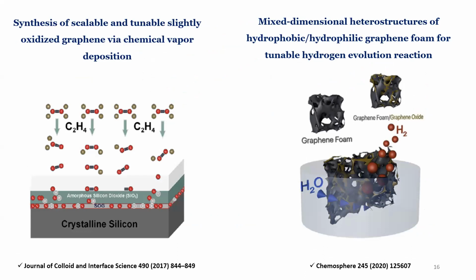I also worked on CVD prepared graphene. We published 2 papers here. In one, slightly oxidized graphene was prepared using CVD, and it was compared to chemically prepared graphene oxide. And in the other one, graphene oxide dispersion was dropped onto the graphene foam. That's why we call that mixed dimensional heterostructure. And it was used in hydrogen evolution reaction.